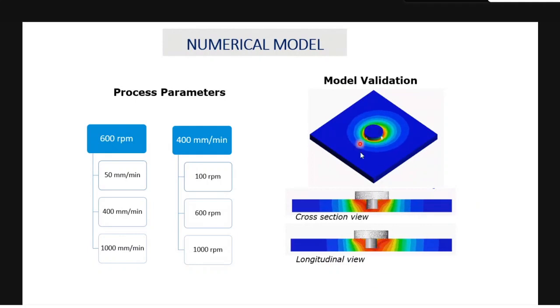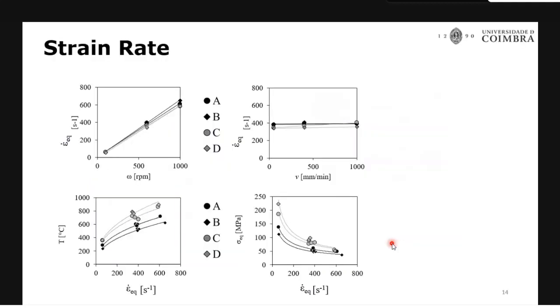So you can see here the simulation results, where this is the advancing side and this is the retreating side. The advancing side recorded a higher temperature, which is a well-known phenomenon. And here this is the longitudinal section, with the tool front end and the rear end. You can see a wider, higher temperature region at the tool rear, because this region has undergone welding during the previous instances, so you have heat buildup there. These differences in temperature distribution are rightly predicted by using these above conditions.